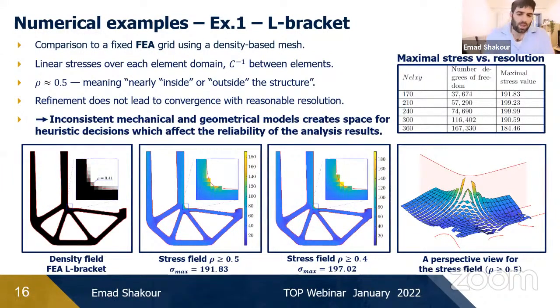Furthermore, we ran the density-based problem with different discretizations, and the results are presented in the table. We could see that changing the discretization leads to smaller and smaller elements near the boundaries, and this leads to undesirable jumps, or differences, between the maximal stresses at the stress concentration region. In general, the inconsistency between the mechanical model and the geometrical model creates space for heuristic decisions, which may affect the reliability of the analysis results.